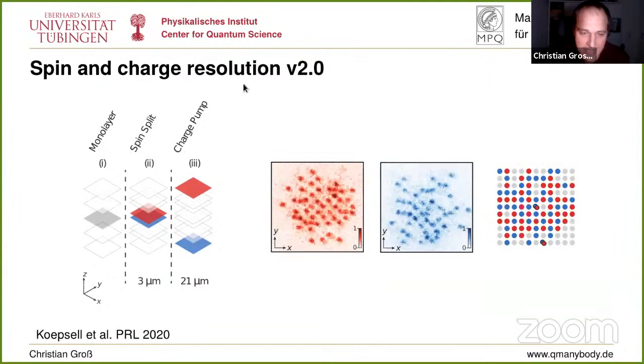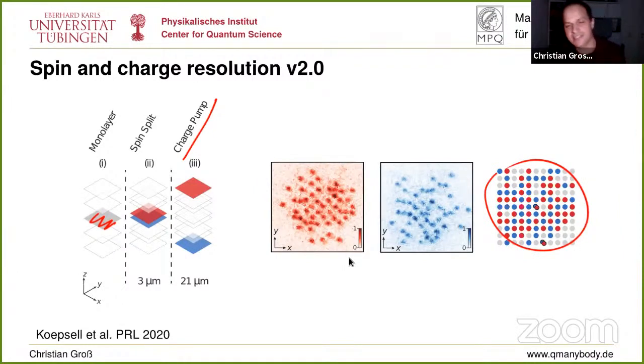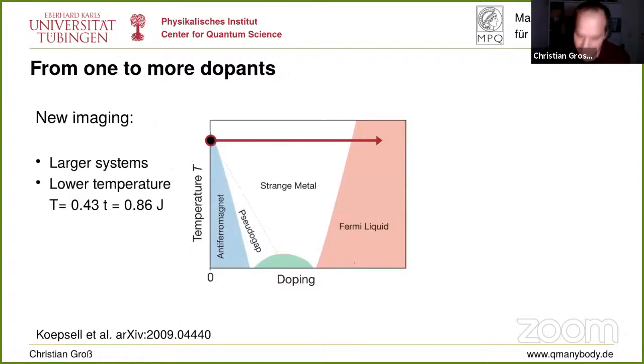We can do that also for spins. So you have now initially basically a spin mixture in one plane. You do this Stern-Gerlach trick in the vertical. And then you move basically the two planes. By the way, that is a kind of trivial Thouless charge pump that we use here. So it's actually even a funny application of a quantum driving cycle to separate these two atom species, if you want, spin species, and then we get these images, and of course we can reconstruct basically the spin distribution in this 2D plane. So this is the technology that enabled the experiments that I'm going to present now.